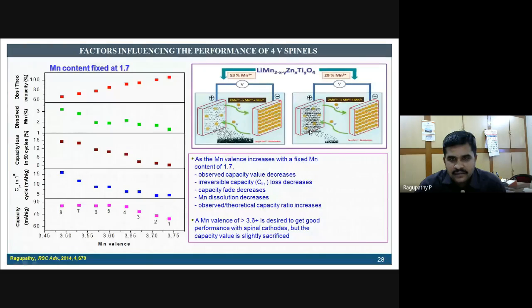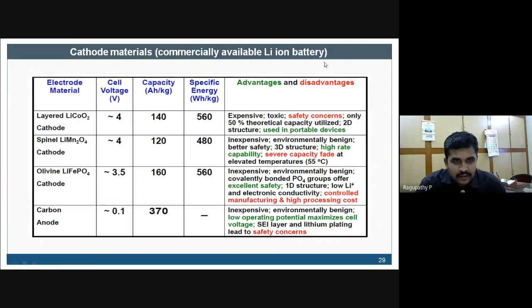The chemistry behind this is that when you have more manganese 3+, the manganese 2+ dissolution will be much more in the electrolyte, because we know that Mn3+ disproportionates into Mn2+ and Mn4+. That 2+ is dissolving in the electrolyte. So here we have fine-tuned the composition of the spinel compound to avoid the maximum dissolution of the active material in the electrolyte. Okay, so this is overall the history of cathode materials.